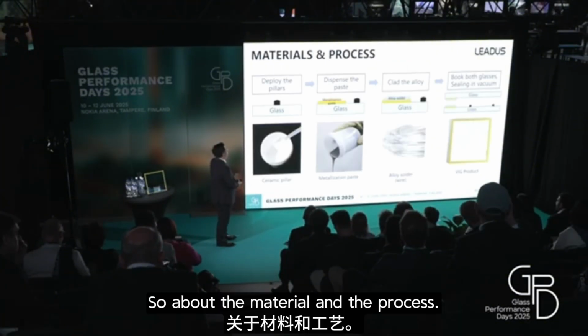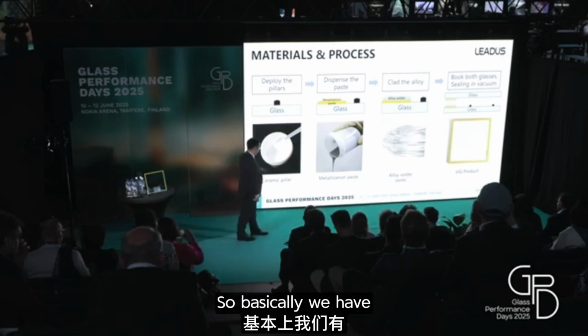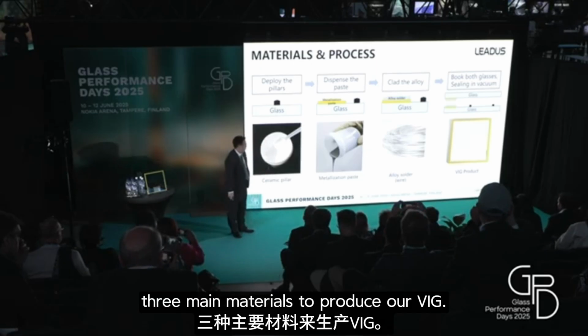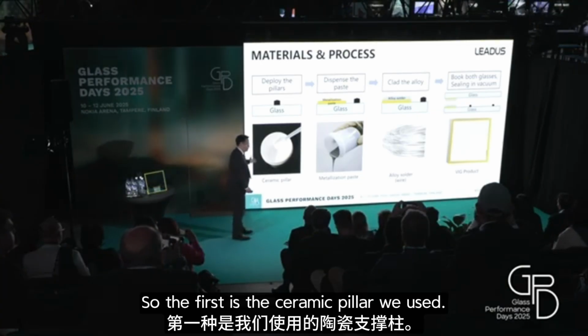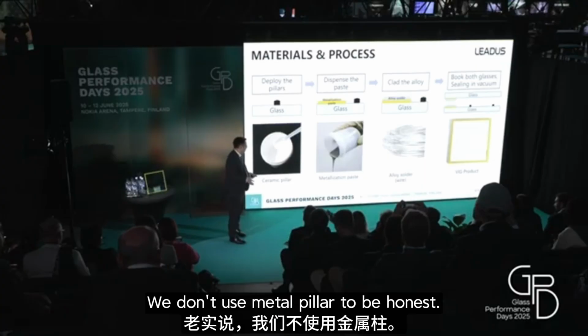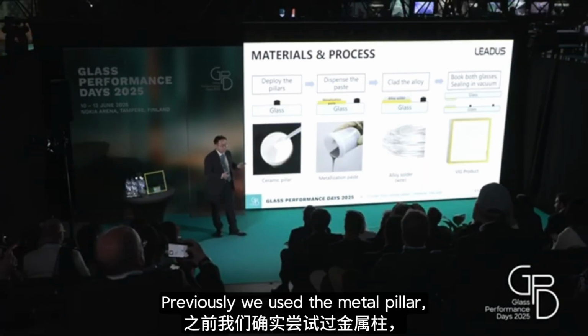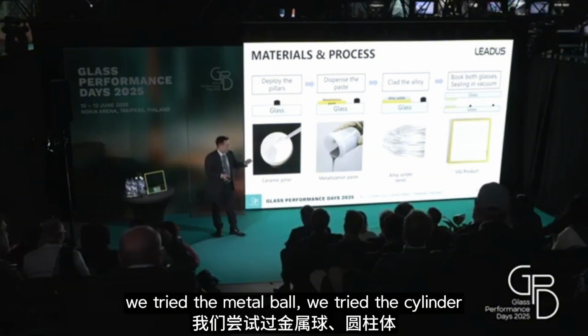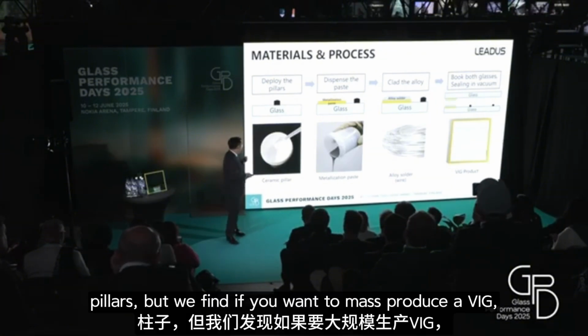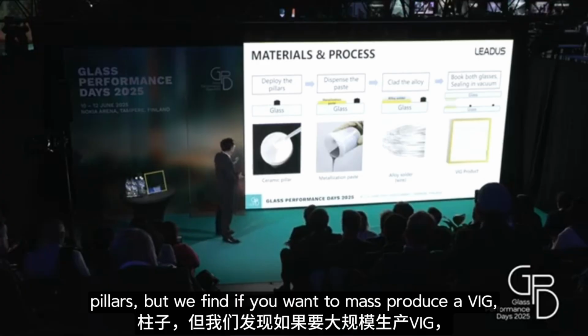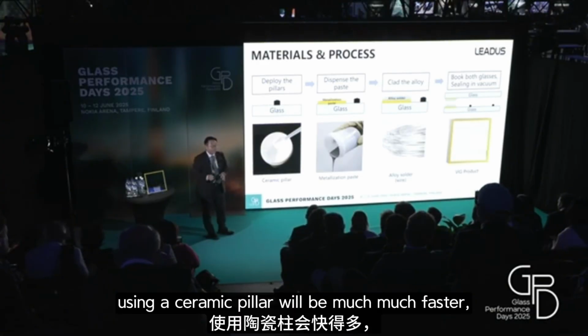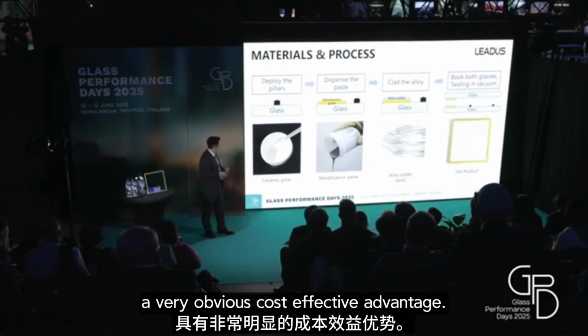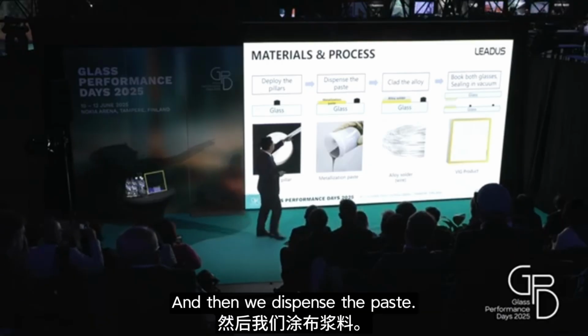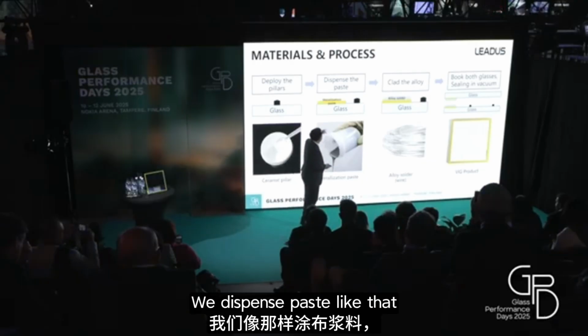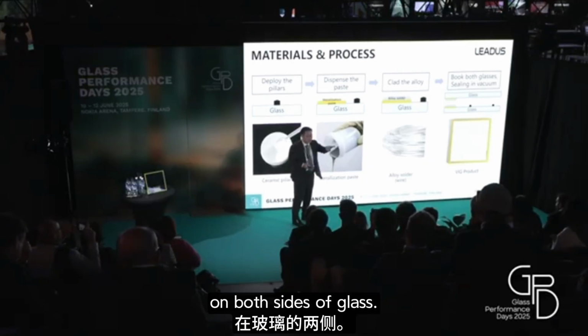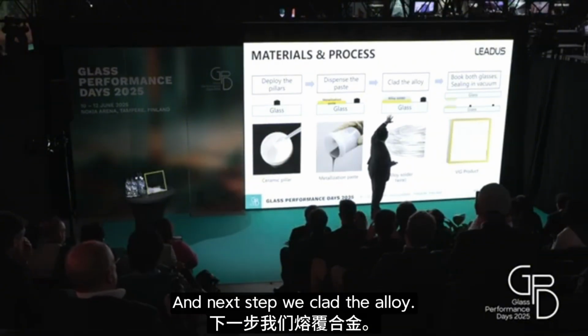About the material and the process, we basically have three main materials to produce our VIG. The first is the ceramic pillar. We don't use a metal pillar. To be honest, previously we did use metal pillars. We tried the metal ball, we tried cylinder pillars, but we found that if you want to mass produce VIG, using the ceramic pillar is much faster, with very obvious cost-effective advantages. And then we dispense the paste. We dispense paste like that around the edge of the glass, on both sides of the glass. And the next step, we clad the alloy.